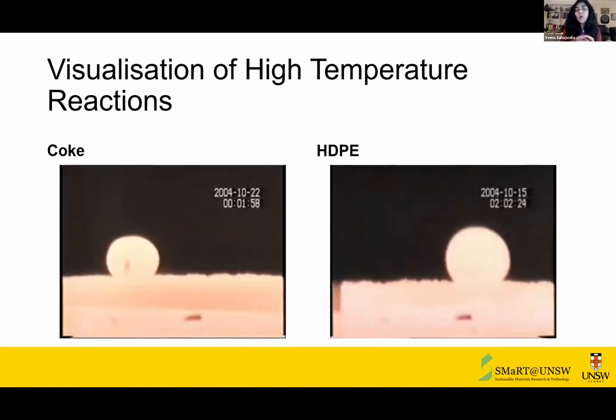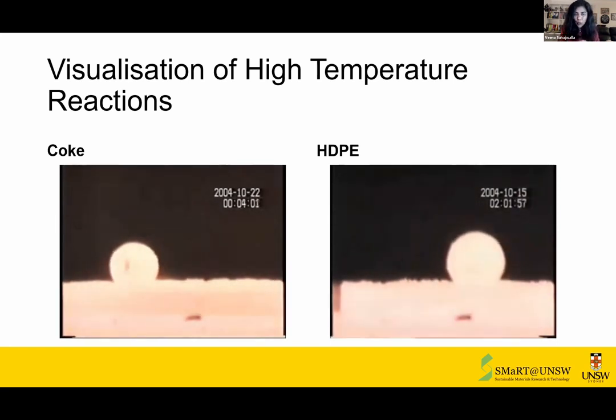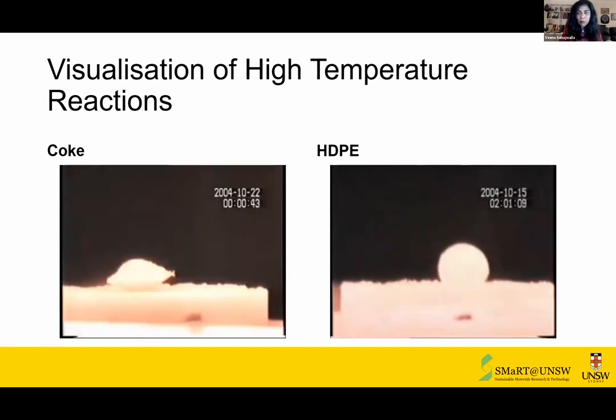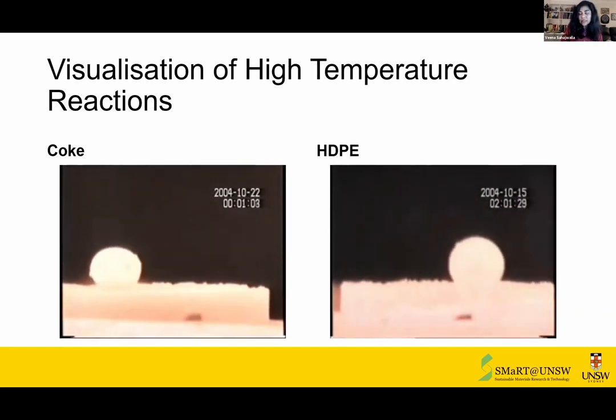And also importantly, that slag forming reaction that you're seeing there, that bubbling phenomenon, using HDPE in this particular research to show that example, is so much more effective compared to coke. The volume of this slag forming is indicative of the fact that the reactions are happening far more efficiently when we use these kinds of polymer blends inside our steelmaking furnaces.